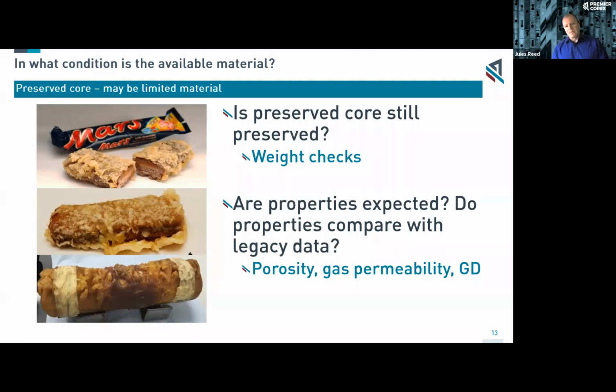Once we've obtained samples from that, and this could be a whole core sample, or it could be a preserved core plug sample, 1 inch or 1.5 inch, once we start preparing those samples and we do cleaning, or we make some measurements of porosity or permeability, we should compare those properties back to our legacy data. Are the properties equivalent to our legacy properties? If not, then our samples may have changed over that time. If they're equal, then there's a good chance that we've got a sample that is usable. And I've known samples that have been used 20 or 30 years after they were originally obtained from a coring process.